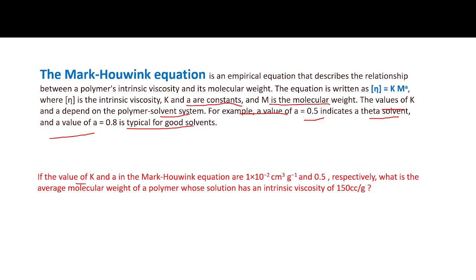So here, what is given: the values of K and a in the Mark-Houwink equation. The K value is 1 times 10 to the minus 2 and a is given as 0.5, respectively. You have to find the average molecular weight of the polymer whose solution has an intrinsic viscosity of 150 cc per gram. So here the intrinsic viscosity eta is given as 150.